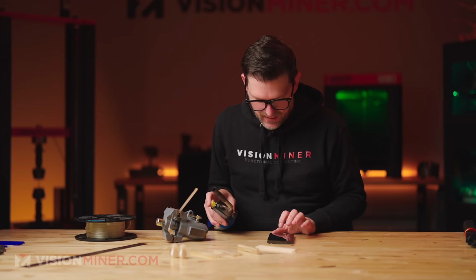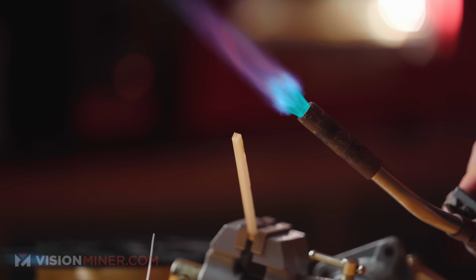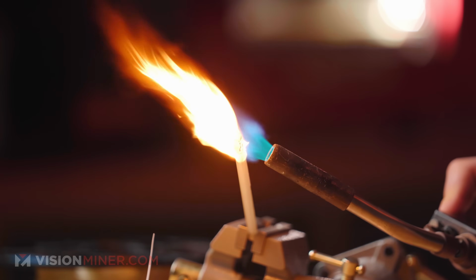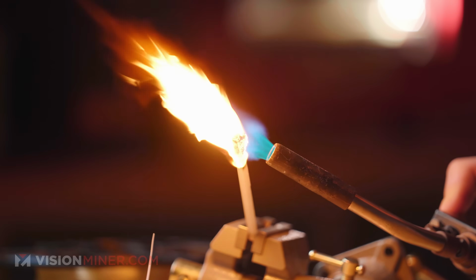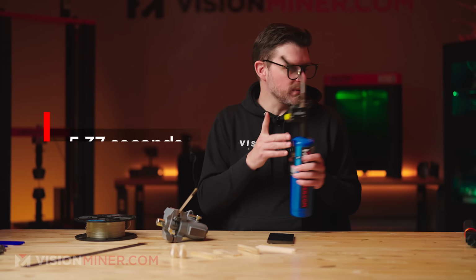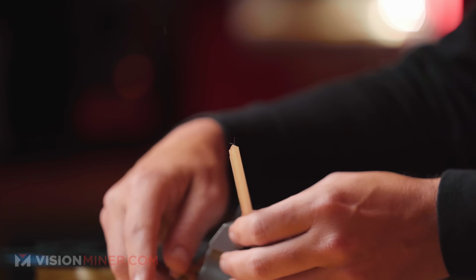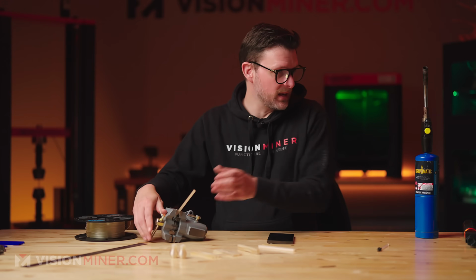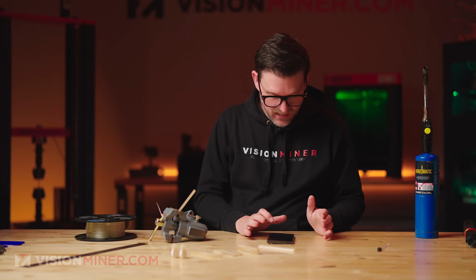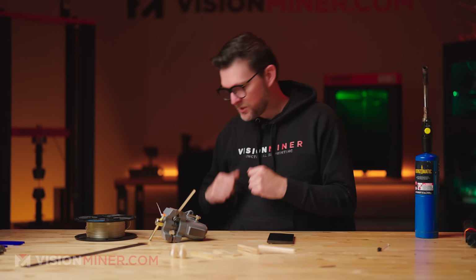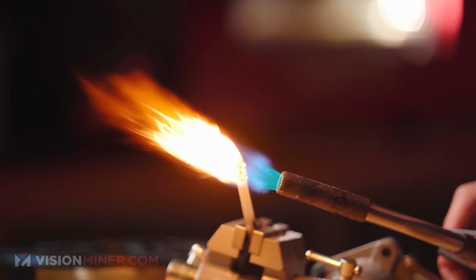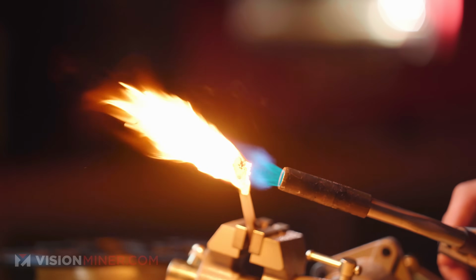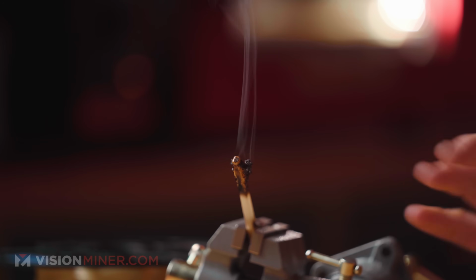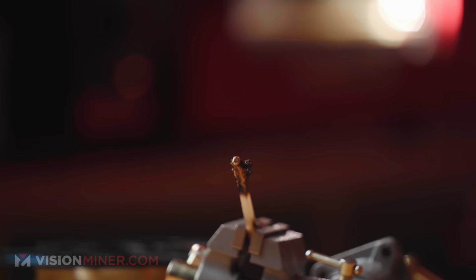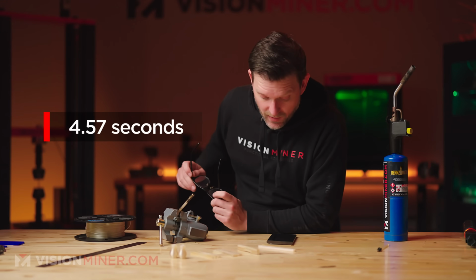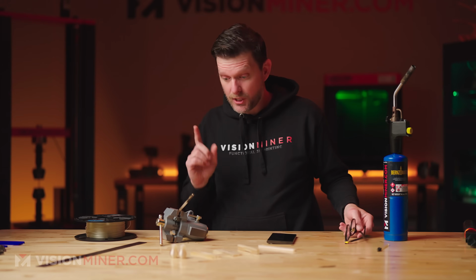All right. And time begins now. .37, so 5 seconds again at a distance of 1 inch with a propane torch on its highest setting, and we got it. I'm going to see how long it takes to actually stop smoking. .57 seconds, so around 4.5 seconds for it to stop smoking.